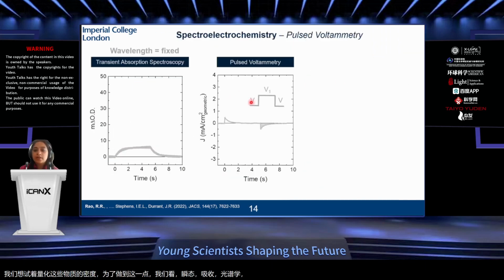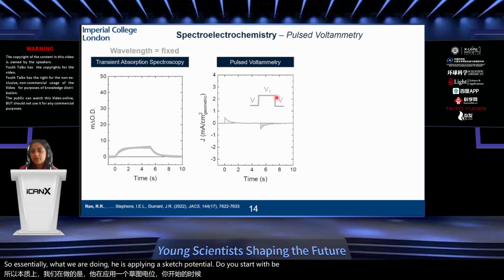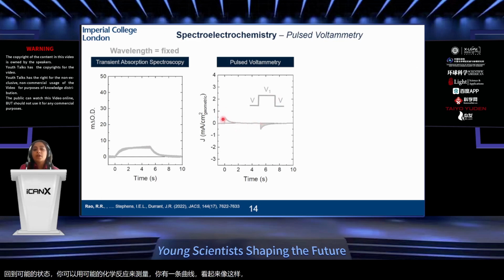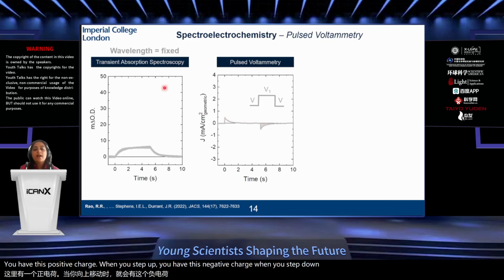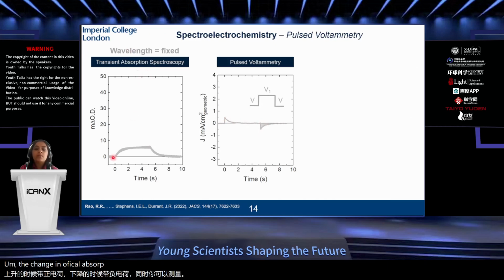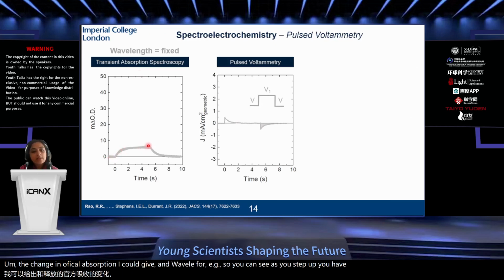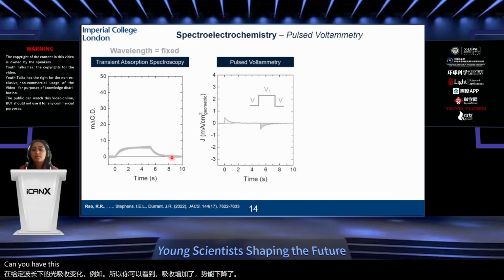So essentially what we are doing here is applying a step potential. You start with V, apply a step potential V1, and come back, step down to potential V. And you can measure with pulsed voltammetry. You have a curve that looks something like this. You have this positive charge when you step up. You have this negative charge when you step down. And at the same time, you can measure the change in optical absorption at a given wavelength, for example. So you can see as you step up, you have this increase in absorption. And as you step down in potential, you have this consequent decrease in absorption.